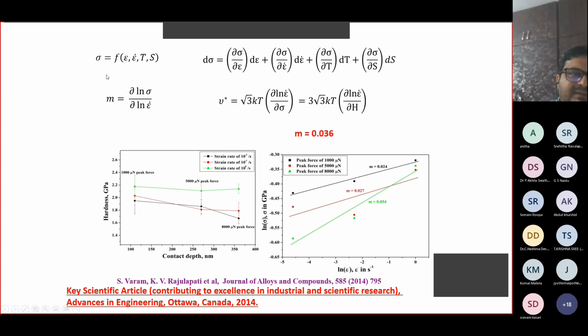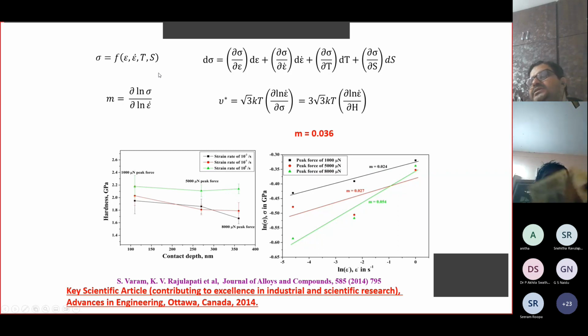And I mentioned before that your flow stress sigma is a function of epsilon, that is strain, epsilon dot, strain rate, T, temperature, and S, the microstructure. Different microstructural parameters are put together into S. So when you vary epsilon, epsilon dot, temperature, or microstructure, sigma gets influenced. When you make a cumulative effect of all these things, it gets represented by this equation. And m is a parameter which you call strain rate sensitivity. At a given strain, if you vary epsilon dot, we'll see what sort of change happens in sigma. And that m value tells you whether your given material is reasonably ductile or not. And the activation volume, V star, its magnitude tells you what sort of lattice defects have helped in making these materials ductile.